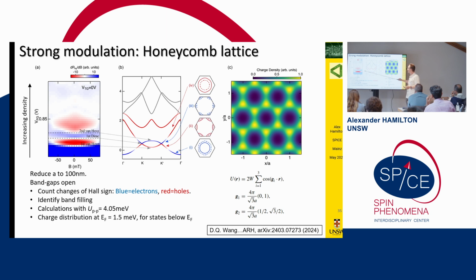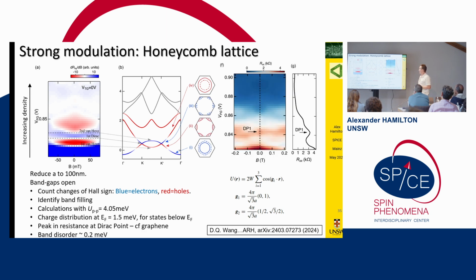We get the potential modulation. Peak-to-peak potential modulation is about 4 millielectron volts. Our Fermi energy is about 3 millielectron volts, or 1.5 millielectron volts. And you will say, if I've got a Dirac point here, shouldn't I have a peak in the resistance where I form a Dirac point?